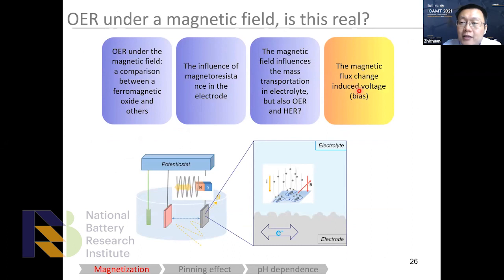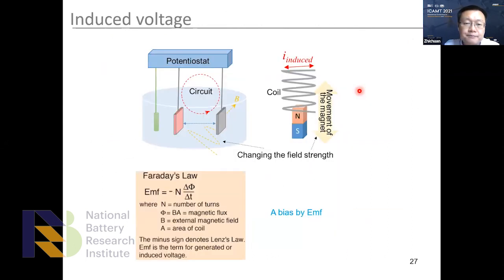And then we can look at the last parameter, that is the magnetic flux. This is because if you look at this potentiostat, this is our measurement setup. So basically, they form a circuit, right? And when we apply the magnetic field, when we have the field on and the field off, or even from nothing to some field, that means the magnetic flux is changed within this circuit. And in this case, based on Faraday's law, we know that a bias will be generated on this circuit. It can be a bias applied on the working electrode. So although we apply the potential on the working electrode, the real potential applied could be different because of the magnetic field.